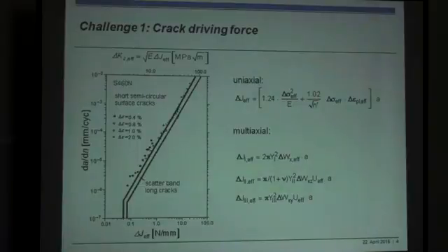We invented our own formulas, more or less, but others did in the same way. We figured out what is the mode 1, opening mode 1, and according to the opening mode 1, we said, okay, let us identify the strain energy density related to the mode 1 direction, multiply that with some geometry factors of the crack length, and do similar things for mode 2 and mode 3.